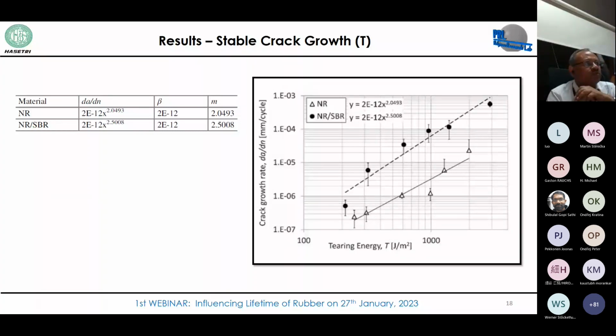And throughout the tearing energy zone, the NR has a lower crack growth rate compared to the NR SBR compound, which is also explainable from the previous work, as well as from the theoretical point of view, that after a certain tearing energy level, NR is having a better crack growth resistance due to the strain-induced crystallization effect. And this table also gives the material parameter from the power law model as well.